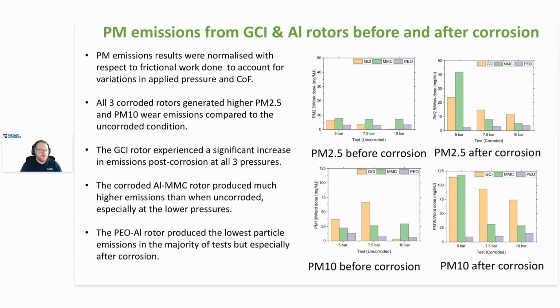Okay, and finally, turning to emission results. One important point is that the PM measurements have been normalized with respect to the total friction work done in each test to allow for the varying coefficient of friction. The histogram plots show mean PM2.5 and PM10 emissions before and after corrosion in each case to the same scale. The substantial increase in emissions for the grey cast iron rotor after corrosion is very obvious from these plots, as we can see there on the right.